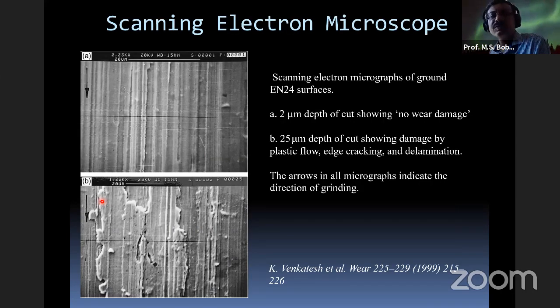And the scanning electron microscope directly shows you the roughness. You can see that the bottom surface is rougher than the top surface. Immediately on seeing it, you can detect that. The top surface is also ground, and the bottom surface is also a ground surface of, I think, steel. The depth of cut in the bottom one is very high. Because of that, there is huge deformation, a lot of plastic flow and edge cracking. Whereas in the top, there are still grooves formed by grinding wheel grits rubbing against the metallic surface. They form plowing marks or grooves, but they are all nicely ordered. This kind of thing also helps, but it hardly gives us any quantitative numbers on the surface roughness.